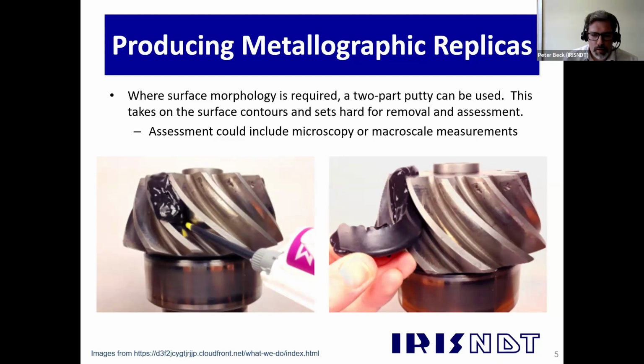The disadvantages are that it's not flat. I mean, that's quite obvious, but typically the way we assess things is by optical microscope, so we would generally look for a flat surface. So this isn't what we typically use. But if you did need to use this, it can be for corrosion pits, things like that, casting defects, those kind of imperfections that are volumetric and three-dimensional. So that's one method of replication.